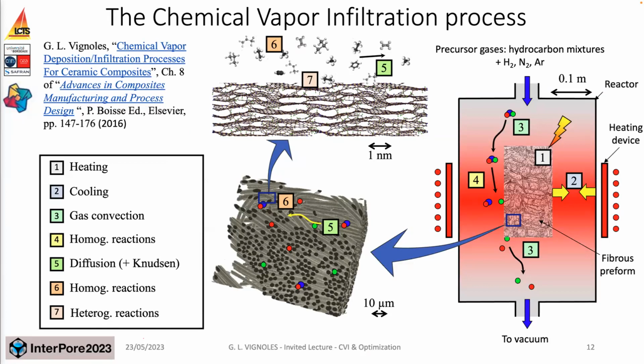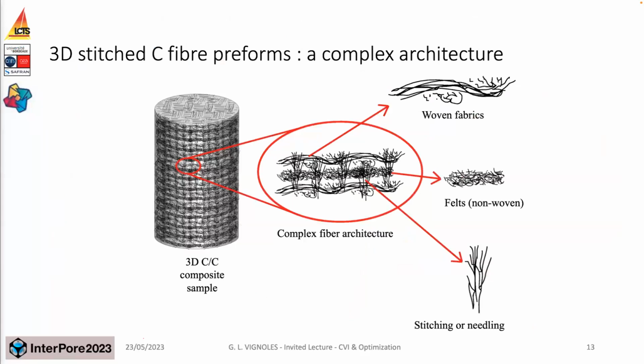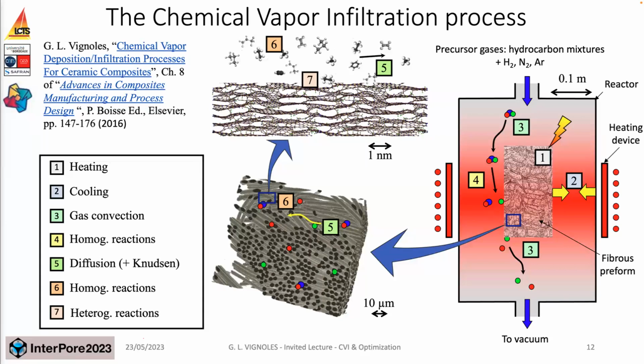Okay, what is the chemical vapor infiltration process? It's like this. You have a furnace, a reactor chamber in which you allow precursor gases. For example, if you want to deposit carbon, you just put hydrocarbon mixtures inside, plus hydrogen, argon, and dilution gases. Then you have your porous medium in the middle here, which is heated by different means, and then the gases will enter. So the gases enter the porous medium, and then they are subject to pyrolysis, and in the end, they will react with the porous medium surface. They will leave a solid deposit, so you will have growth of the solid, and there are some gaseous byproducts that are evacuated from this medium to the outlet.